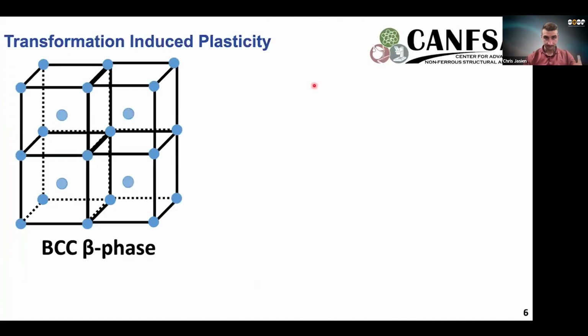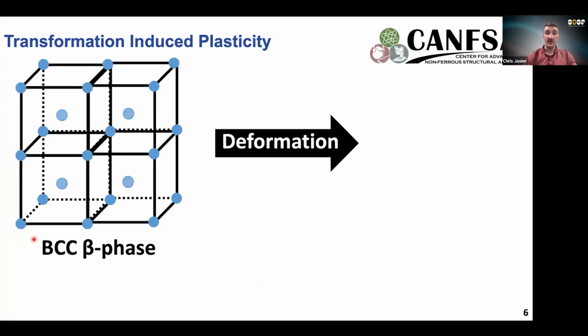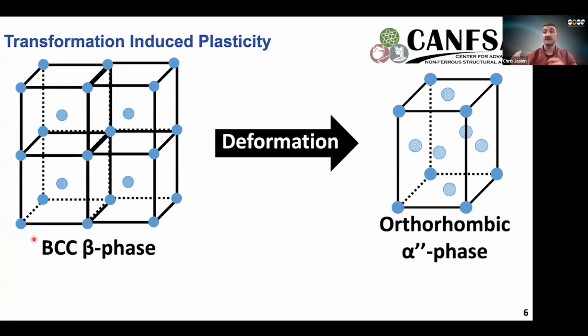And so what's actually occurring is that the material does solidify and maintain that single metastable beta phase, which is oriented in the body-centered cubic atomic structure, just outlined here. But when you apply some amount of deformation, it allows the material to transform into this martensitic, lower symmetry orthorhombic phase. And so we didn't apply any external deformation to this material. So this further begs another question: where did this deformation arise from to cause this transformation?